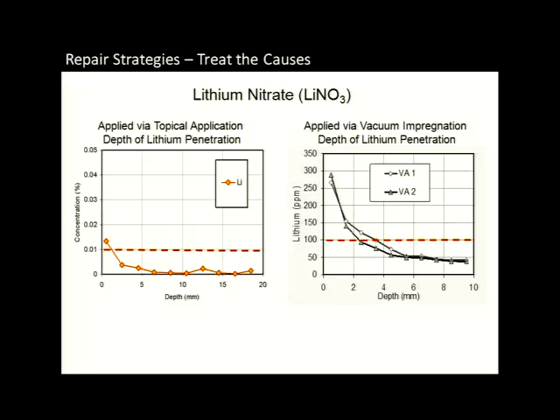And what you can see is that in the topical application, you only get lithium down to about 2 millimeters. So if you think about 2 millimeters, it's about that big over the width of an entire one of these Jersey barriers that may be anywhere from 150 to 300 or 400 millimeters thick. And then you really just get down to background levels at depth. As a point of reference, 20 millimeters isn't even a full inch into the structure. If we look at vacuum impregnation, certainly a lot better in this case. We're getting it down to about 4 millimeters, but we're still not getting it into any appreciable depth in the concrete. So this was certainly of big concern to us, that we're not getting the lithium into the concrete that we really need to control the reaction.